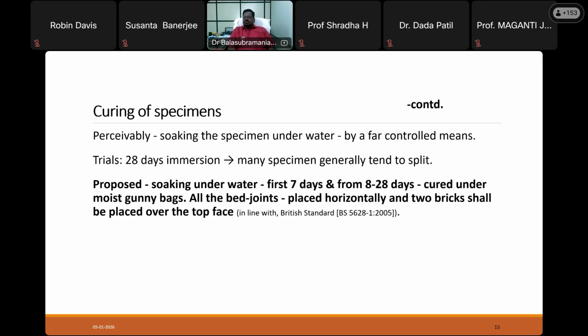Alternatively, for the first few days we can keep the specimen soaked under water, and then beyond that we can place the specimen covered with moist gunny bags. But supposing we are using the soaking underwater method, we will have to place 2 bricks on top, to have some minimal compressive stress, so that the soaking doesn't separate the specimens. In some cases, if we keep the specimen under water for a long time without this kind of pre-compression, separations have happened.